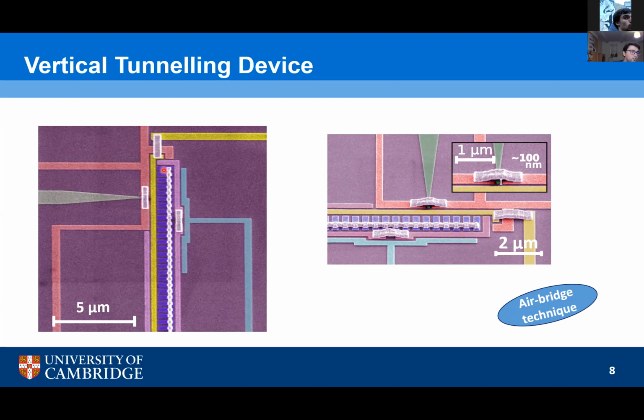The second E-beam stage, you need a 3-layer resist stack, which needs to be very well calibrated in terms of thickness to fabricate these bridges. Now, the good thing about these bridges is that once your calibration is good, and it took me about 2 months to get that calibration right, it's an incredibly reliable technique. So you can see under an optical microscope if the bridges are there. They very rarely break. It's either everything's broken or nothing's broken.